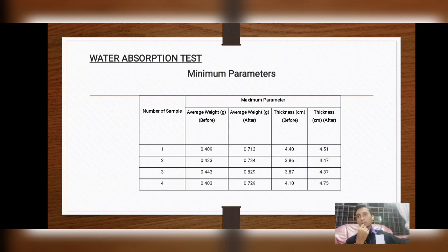The second result is about the effect of different material parameters on the water absorption test. The water absorption test is one of the tests that were conducted in this research project other than the tensile test, and this test was done according to ASTM D570 for coconut coir. The results obtained for the water absorption test were slightly different between minimum and maximum parameters. Based on the observation, the average weight for the minimum parameters of the sample increased after the experiment.